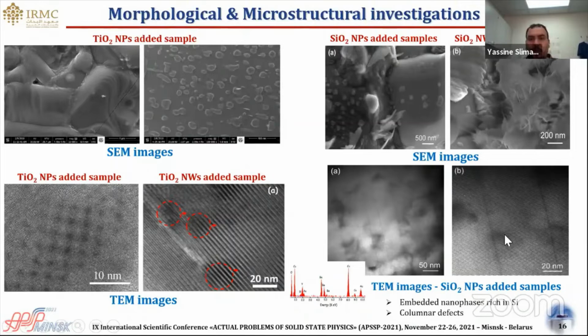We present here also an example of the effect of including insulating nanomaterial such as silica oxide. Interestingly, the TEM micrograph of YBCO sample added with silica oxide nanoparticles showed the presence of nanophases rich in silica embedded within the YBCO superconductor, as well as the appearance of interfaces and columnar defects that could effectively contribute more to the pinning of vortices.